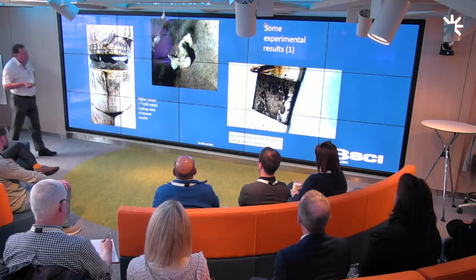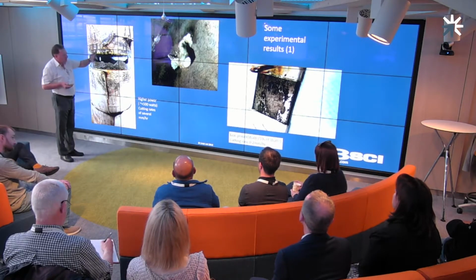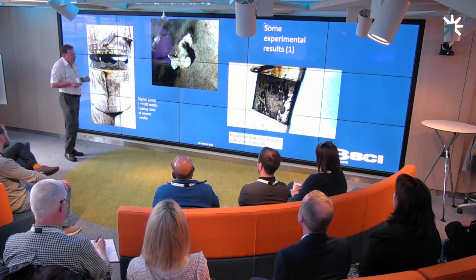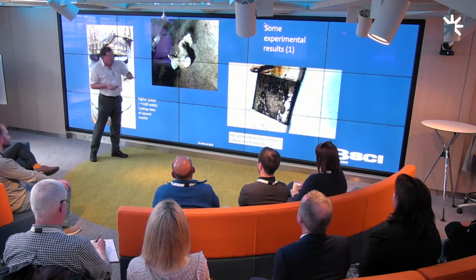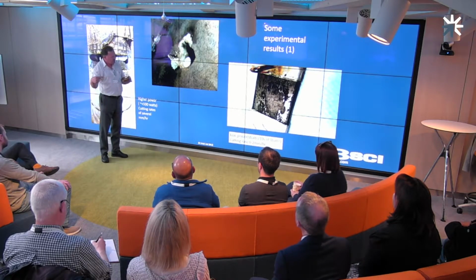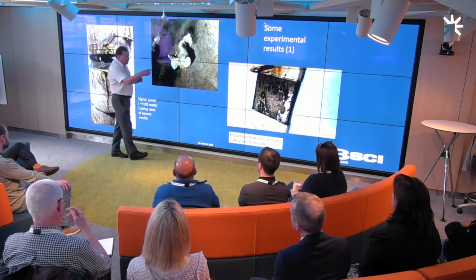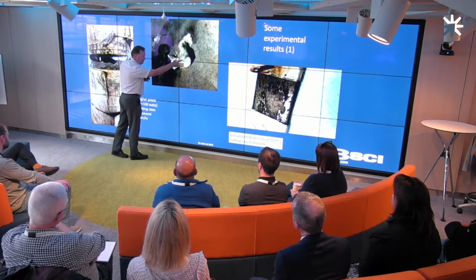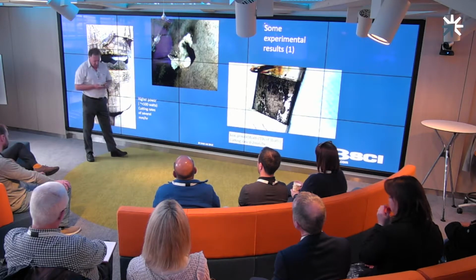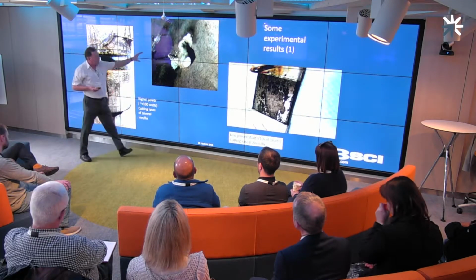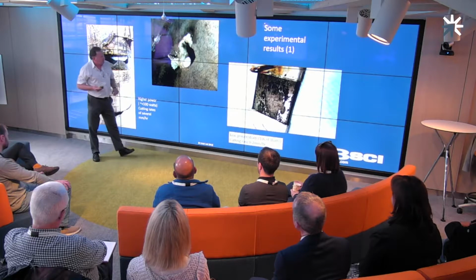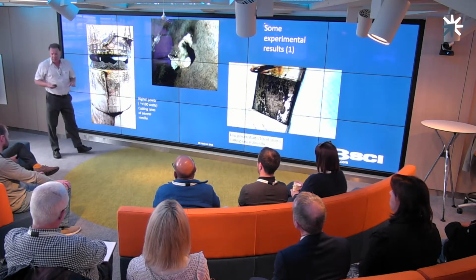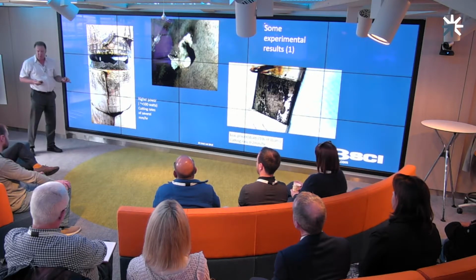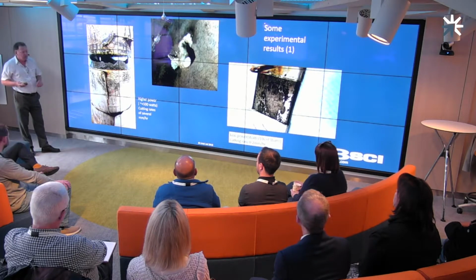So the second example here, excuse the blurry image, unfortunately it was the only one I had, is where we've actually drilled a hole in the steel pipe. In this particular example, the cathode was arranged pretty much as a singular point, a rod, sitting in very close proximity to where the hole eventually emerged. We did a little bit of masking off of the steel around the outside of the hole, but again, it gives you an example of what one can achieve by this accelerated corrosion electrochemical technique.